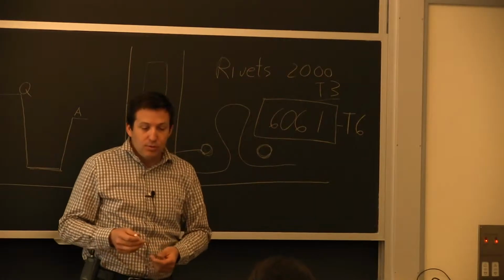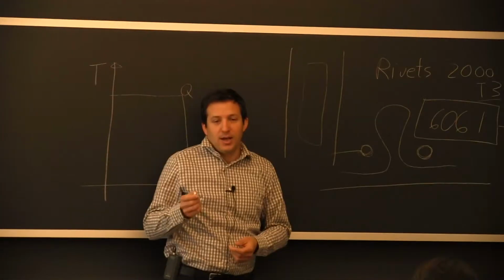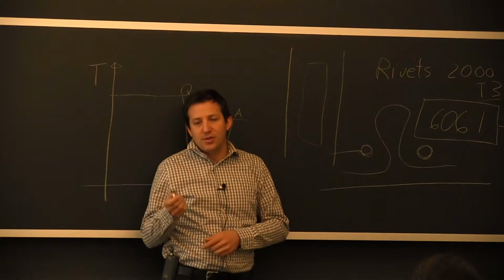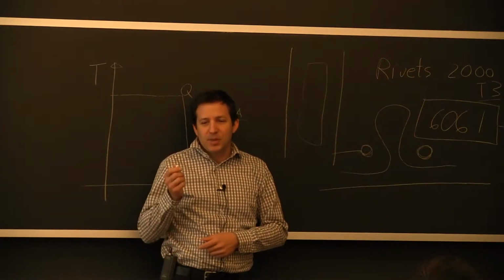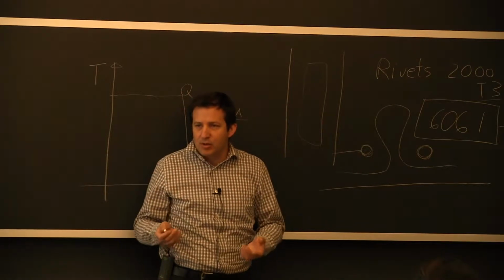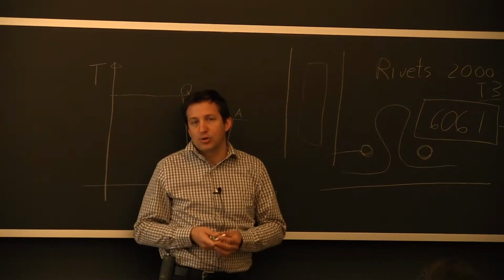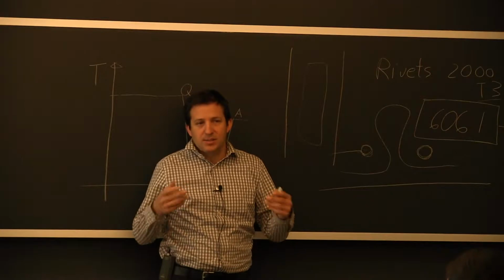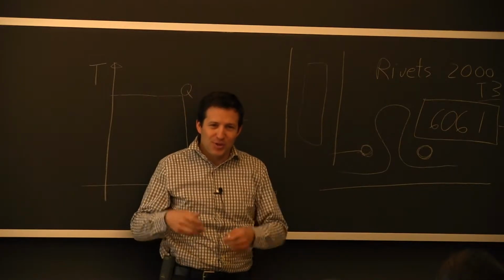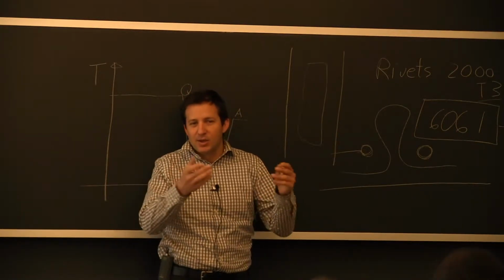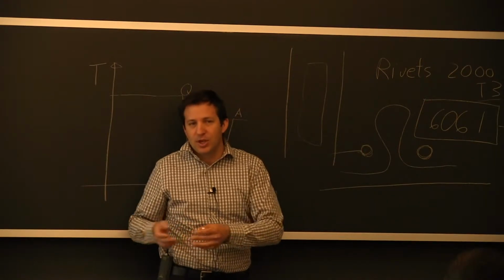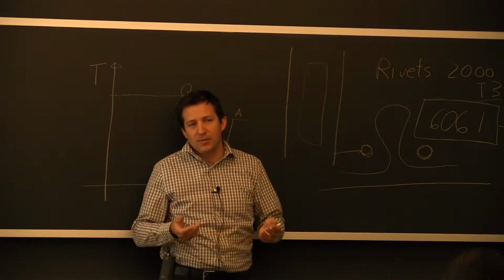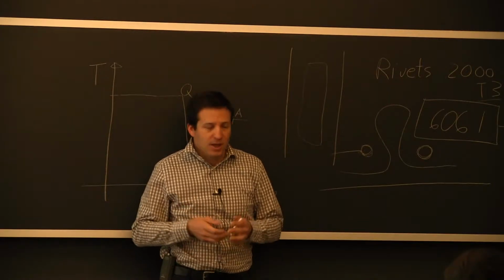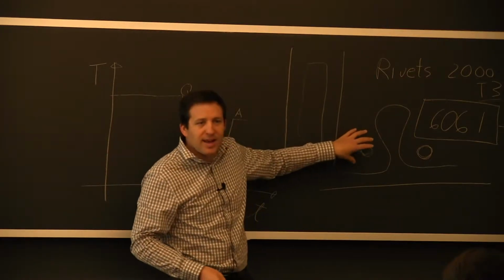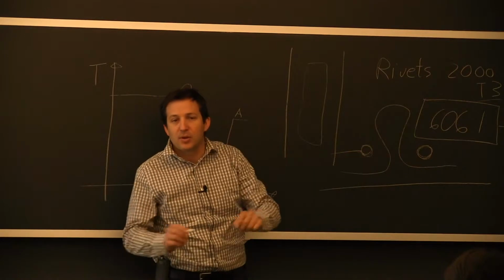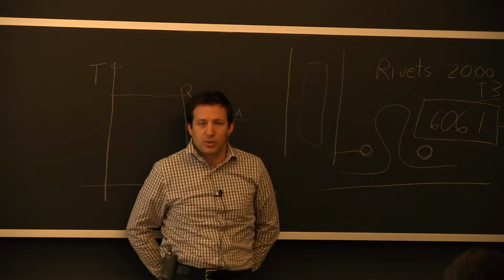We will still use overaged aluminum alloy, especially in the 7000 series, not because of the mechanical performance, but because they have better corrosion resistance. So that always comes into the whole decision-making process where, yeah, you want great properties, but also you need to be resisting pitting if you have chlorides in the environment. And that's what bigger precipitate allows you to do better than if you have a very, very fine distribution of precipitates in the alloy.